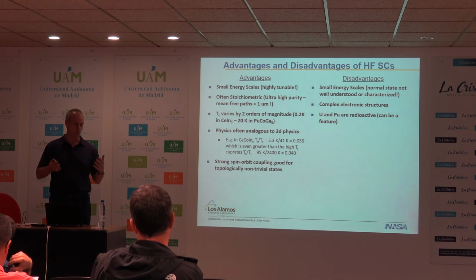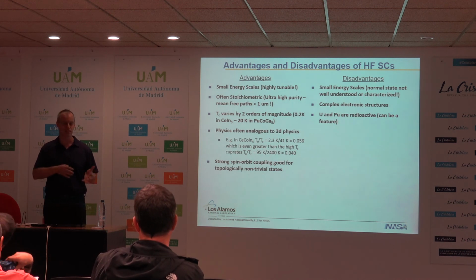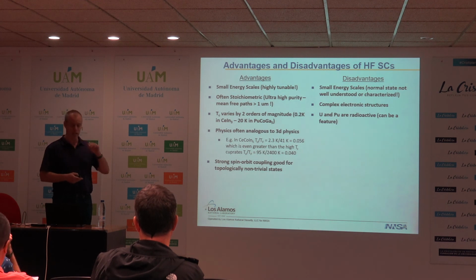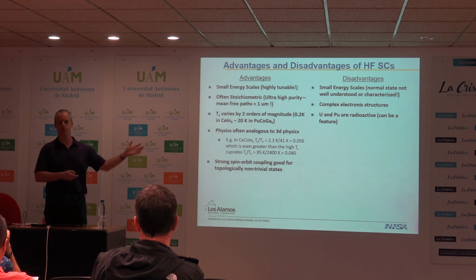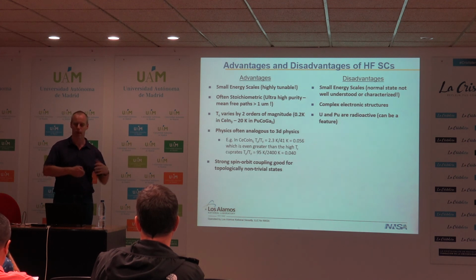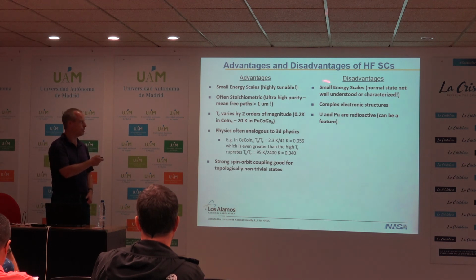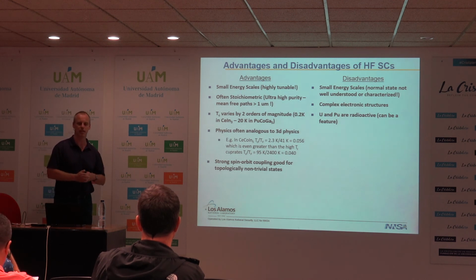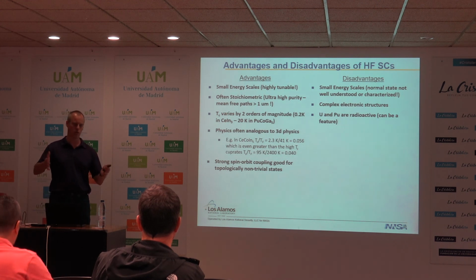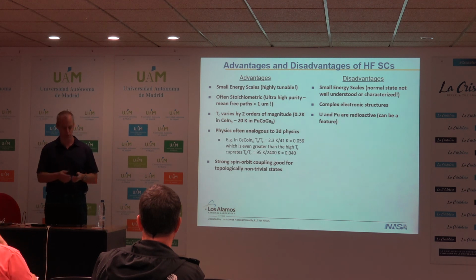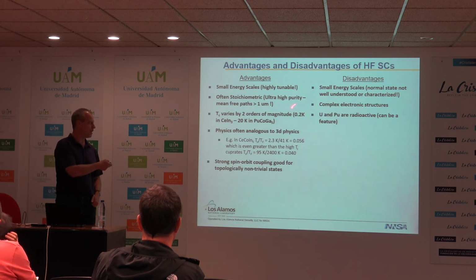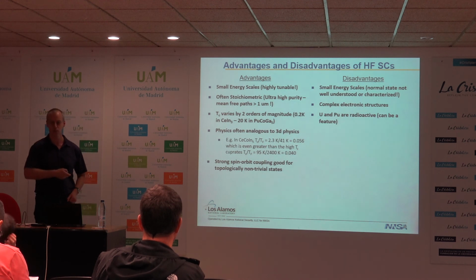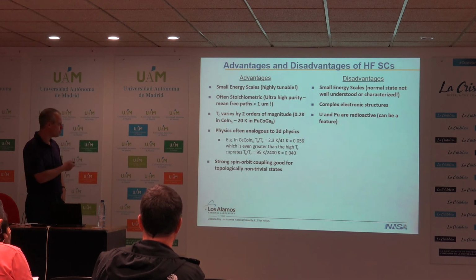So the formation of the heavy fermion state as a lattice phenomenon is not well understood. And it's not even well characterized. We don't have the ARPES data that can map out exactly what the electronic structure is, or what the self-energy is. So that's certainly a struggle. And in fact, the electronic structures tend to be complex. We don't have the single-band version of a heavy fermion, where you just have a large hole-like Fermi surface centered at pi as you do in the cuprates. In general, we have multi-band Fermi surfaces that are quite complex. We know that from the quantum oscillation studies.